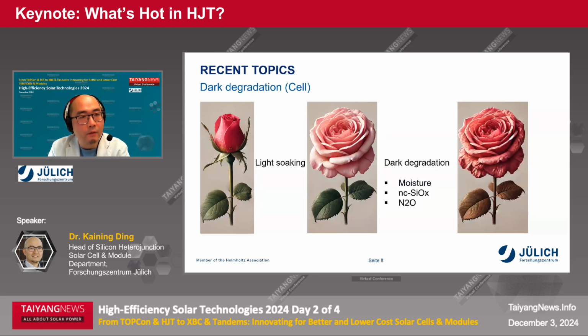And also an important topic at the moment, maybe not the perfect example, is the dark degradation. Usually the solar cell in production undergoes a light soaking process to improve its efficiency. But if you put these cells in the dark, they tend to decrease a little bit in efficiency again. And what is maybe wrong in this example with the rose is that in the degraded state, if you do a light soaking, you will again be able to recover it.